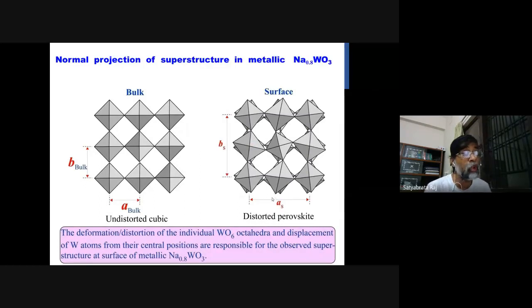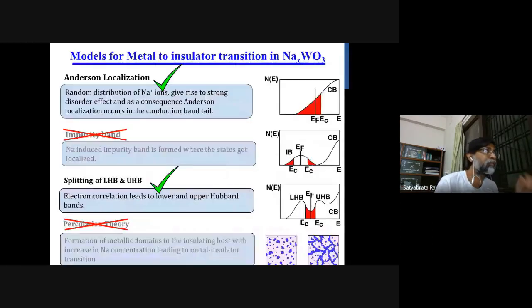And as a result, your A and your B becomes double. That makes this X point becomes the new gamma point. That's why the Fermi surface is duplicating in the X and M point. And this distortion of the WO6 octahedra is because of the deformation of the individual WO6 octahedra, and displacement of the tungsten from its central position in the surface only. But the bulk is very much an undistorted cubic structure.